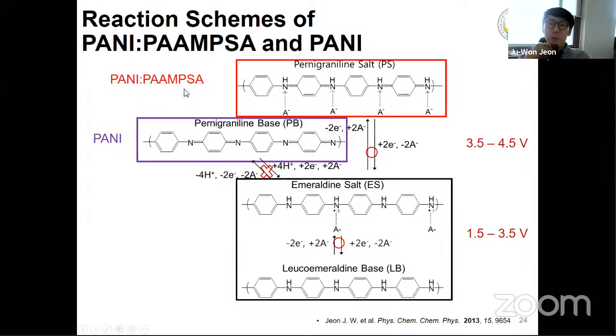But in the case of the PAAMPSA complex, there is a strong interaction between the protonated amine group and the sulfonic acid group, and there is no loss of the proton, so it can be reversibly switched between emeraldine salt and pernigraniline salt, even at a very high voltage like 4.5 volt versus lithium.